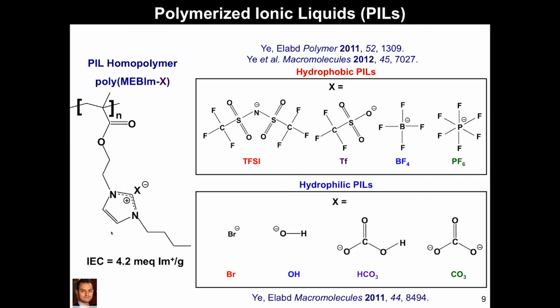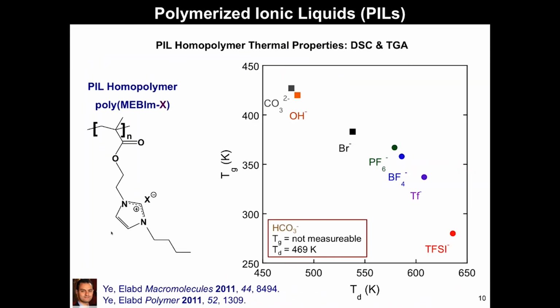And you can also think about other anions. Here I'm showing at the bottom, if you think about halides or carbonates or hydroxide. And what's interesting is if you take the same polymer and do this ion exchange, you can actually go from something that's very hydrophobic to something that's very hydrophilic and can even be water soluble. So just by doing the ion exchange, you can have a significant impact on the hydrophilicity, not just the glass transition temperature. In slide 10 here, you can see this just shows you an example.